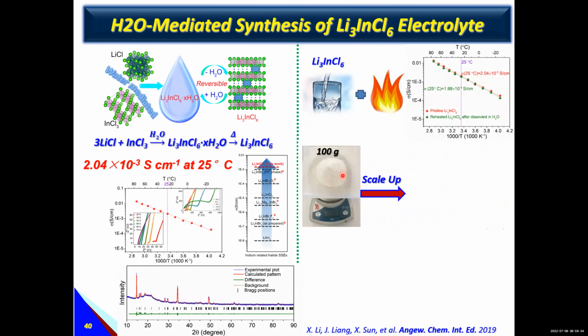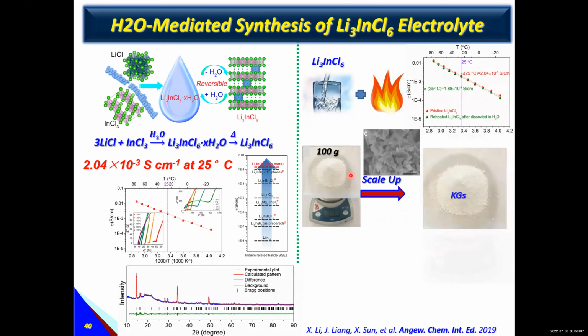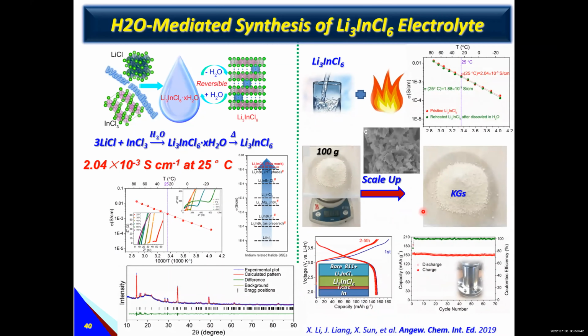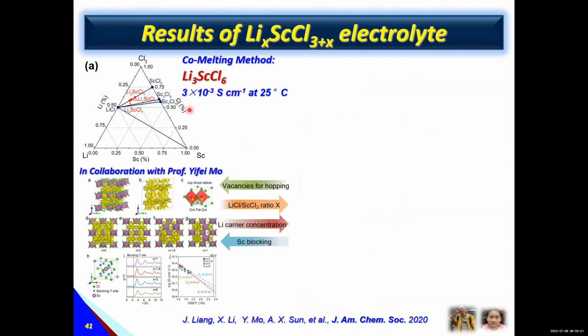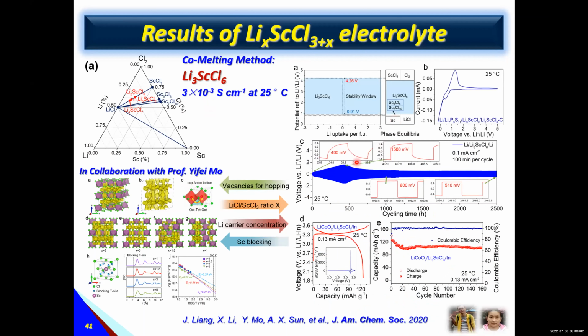When we worked on that in the beginning, we had a small amount. Later on, we have several 10 kilograms level mass production. And we demonstrate that batteries work. But again, we need to protect the anode part. So later on, we worked on lithium scandium chloride, which has a higher ionic conductivity. We have a collaboration with Professor Yifei Mo's group to understand it. Also, this system is interesting because it is stable with lithium metal. In the beginning there is some reaction, later on it's very stable. And we demonstrate the battery model cells work.